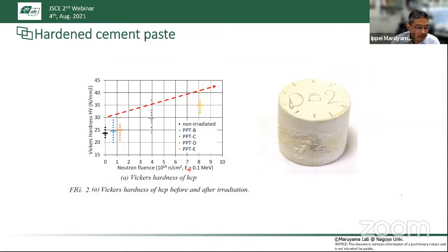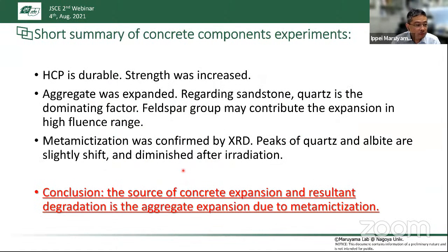And finally, I would like to shortly introduce the result of the hardened cement paste. There is no or almost negligible volume change after the neutron irradiation. And also we see the increase in the Vickers hardness of the hardened cement, Vickers hardness as a function of the neutron fluence here. So therefore, we can conclude that the hardened cement paste is durable under the neutron irradiation environment.